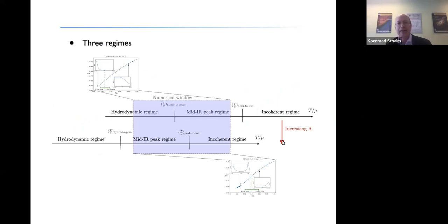Now, strictly speaking, all this linear in T resistivity, you should think of as a continuum. The only reason why I'm presenting it to you in two pieces is because for numerical reasons, we cannot in one model go all the way from this hydrodynamic Drude-like regime to the mid-IR peak regime, and let's call it the incoherent regime. In reality, we believe that if I take a fixed A, there is a complete continuous transition between all these three regimes. However, numerically, for a fixed A, I can only cover two of these regimes. And by increasing the amplitude in the system, I can cover the other two regimes.